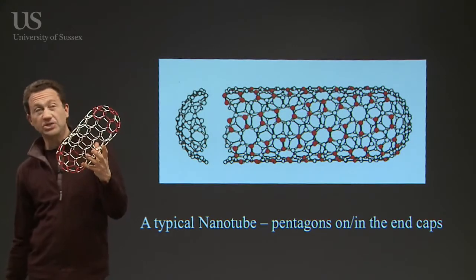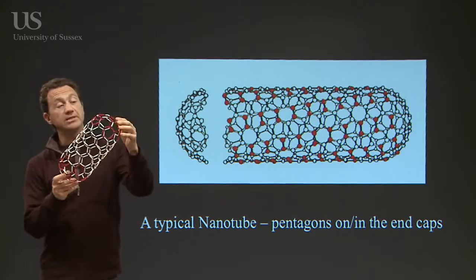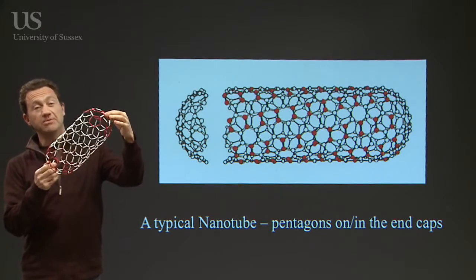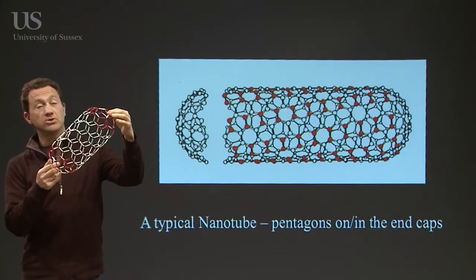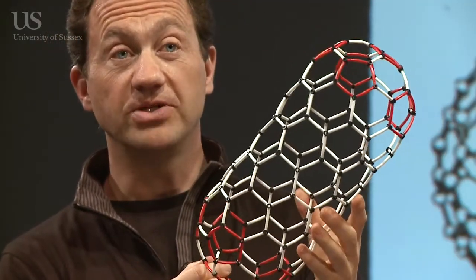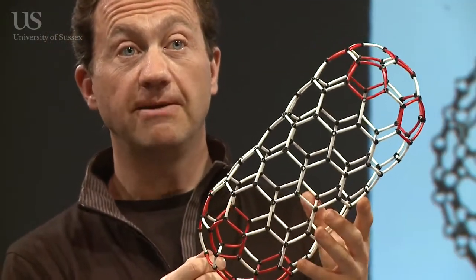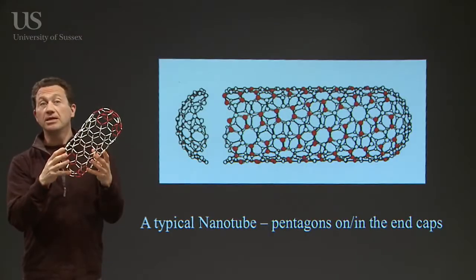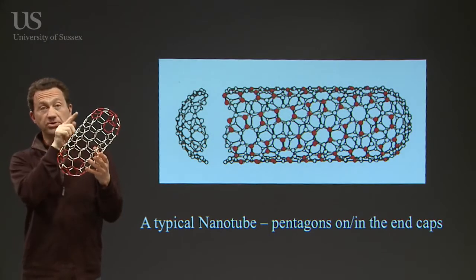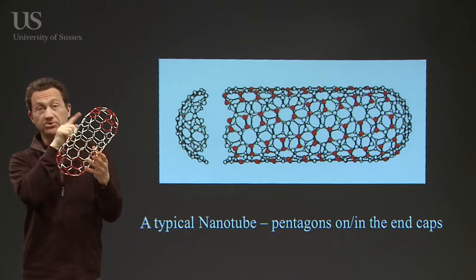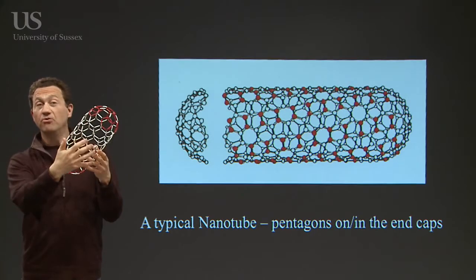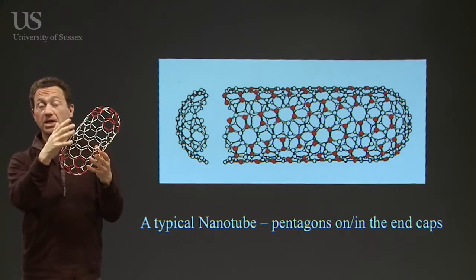So how do you make a nanotube? When you make fullerenes, you vaporise carbon in what's called a carbon arc. You contact two pieces of carbon, put an electrical current through it and vaporise it. If you use a DC arc instead of AC electricity, you get a build-up on one of the electrodes — on the cathode — and you find nanotubes forming in the carbon arc.